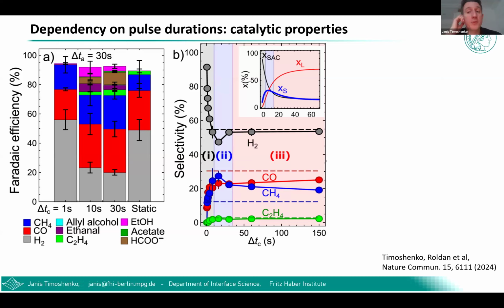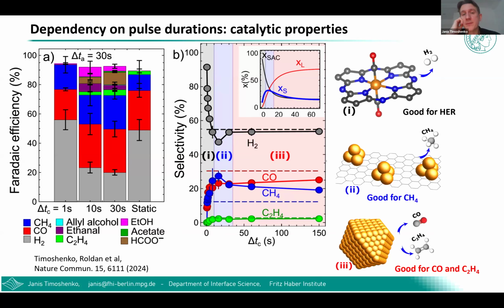So this allows us to propose a quite simple explanation for the observed trends: these thinly dispersed sites are good for hydrogen evolution, but not really good for CO2 conversion, while these bigger particles are good for production of ethylene and CO, but these very, very small clusters are really good for production of methane. So depending on what reaction product you need, you can easily switch between the structures of the catalyst just by changing the parameters of the applied pulse protocol.